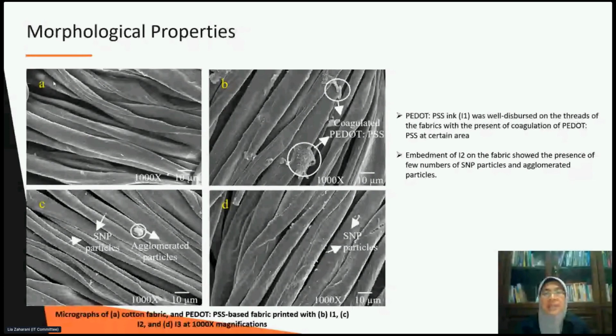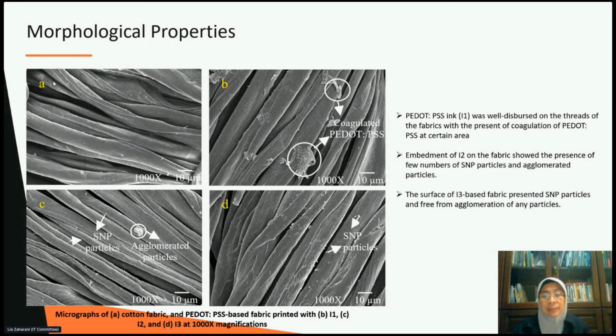This indicated the improvement in homogeneity of ink 3, obtained with the addition of ethanol and EG in the ink formulation. So the results suggested the ink based on PSS has been well embedded on the fabric.